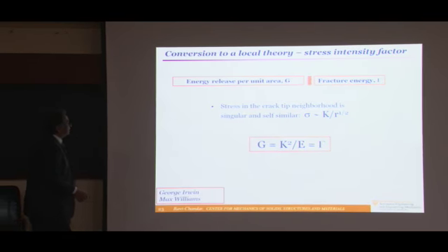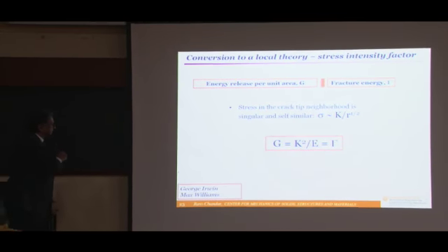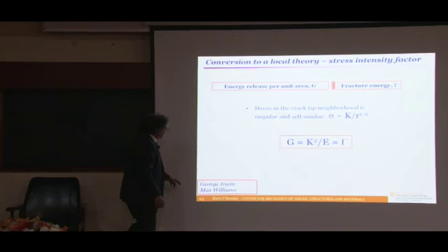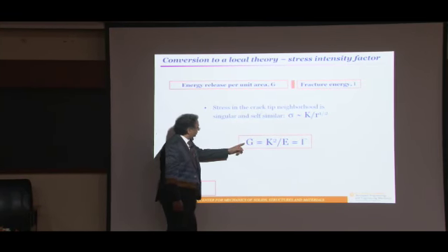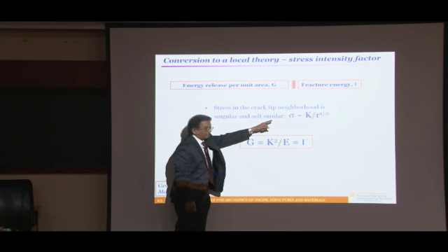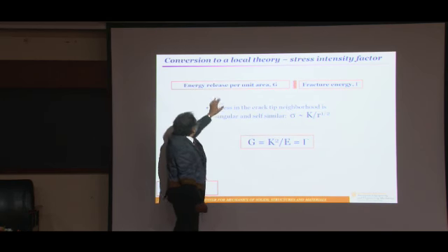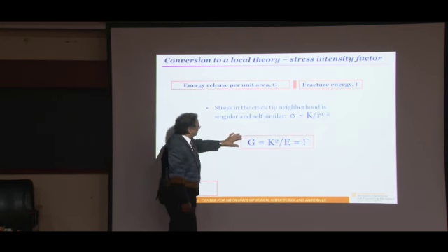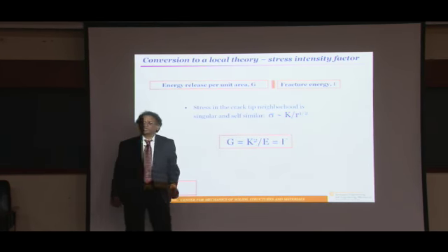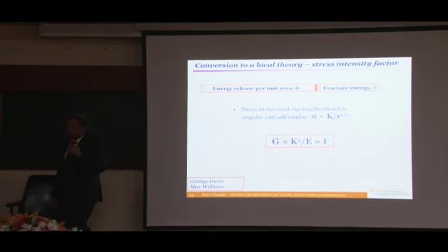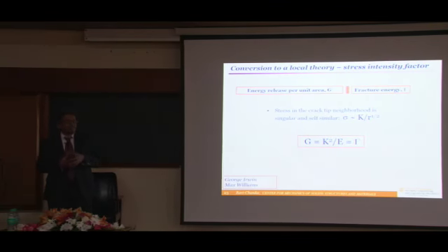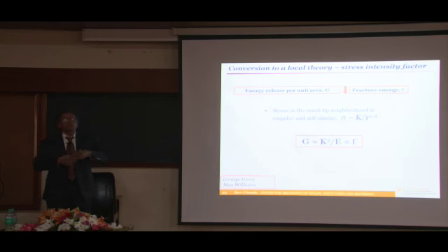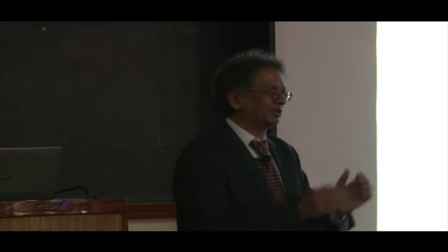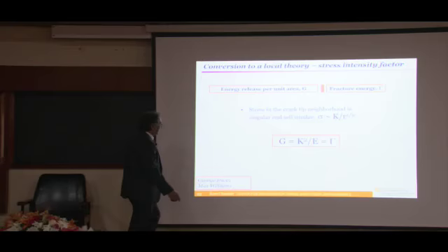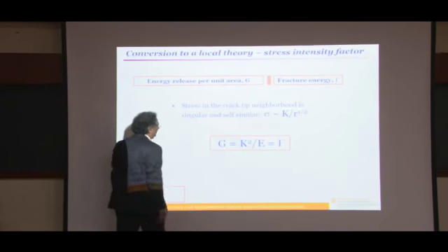This theory has been extremely successful in that we have now structures that are built to be fracture critical, that they obey this criterion. The stress intensity will never exceed this equality. And then you're able to operate airplanes, bridges, automobiles, whatever, under fracture critical conditions, not strength critical conditions. Let's move on a little bit.